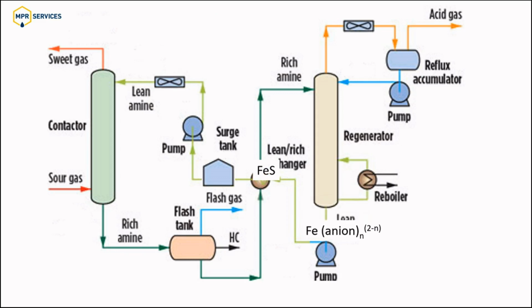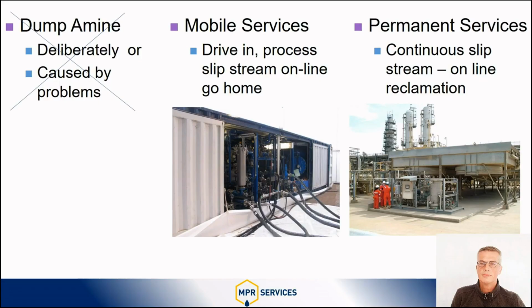The complex travels with the amine to the absorber where it gets overwhelmed by H2S and CO2. The iron drops out of the complex as a freshly formed submicron particle. The free complex former, heat stable salt anion, travels back to the regenerator and does this trick over and over again.